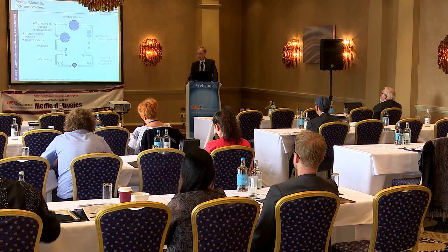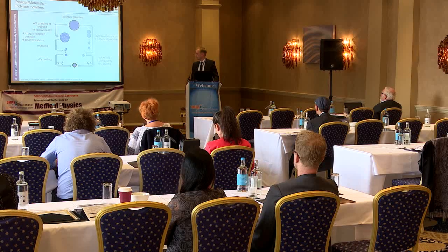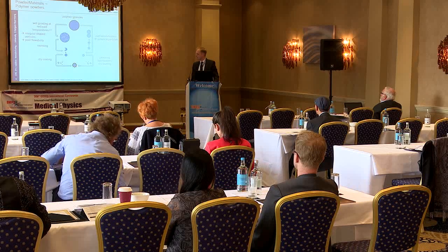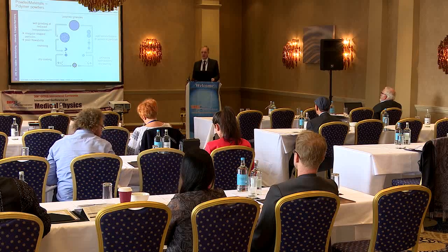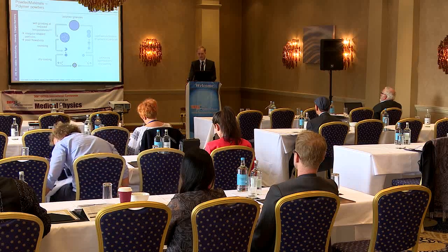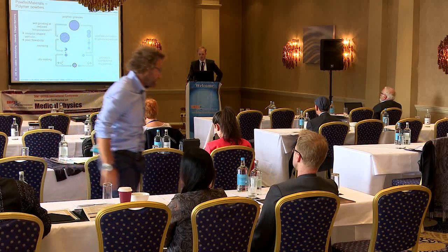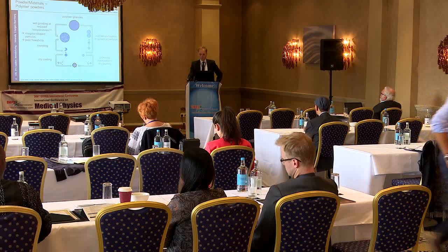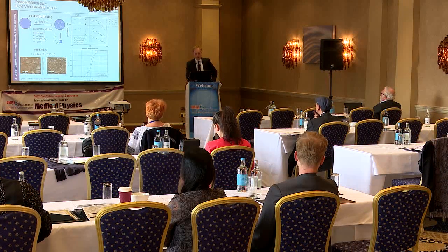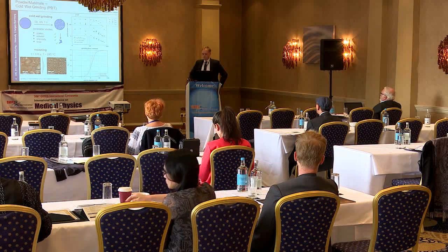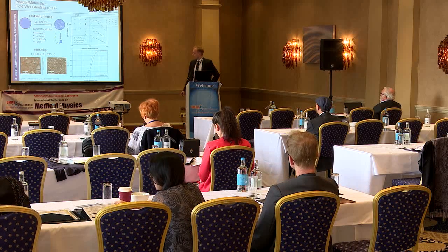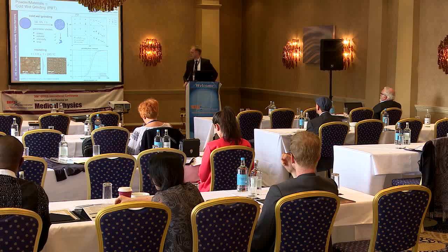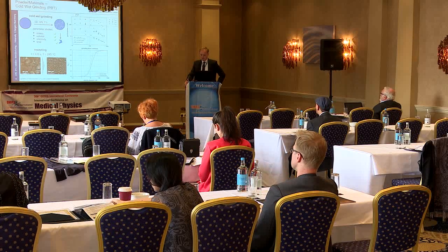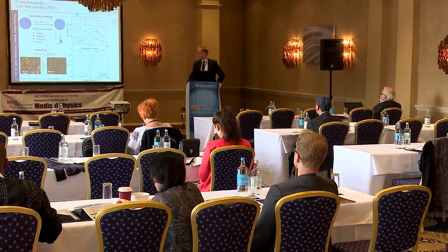So we have a rounding step which was established in our research center to get the particles spherical. And even with this rounding step, we have the possibility to do some particle functionalization, for example, to add a flow agent or to add some other ingredients for functionalizing the material. And as you can see here, in the microscopy pictures on the left side, the very irregular shaped powder can be transferred into this spherical powder with very good packing density and size distributions like the diagrams show.